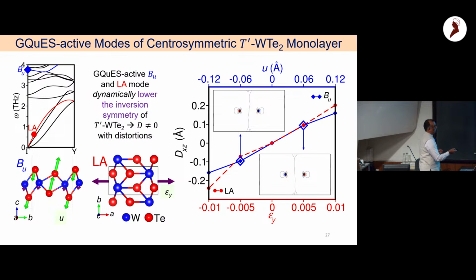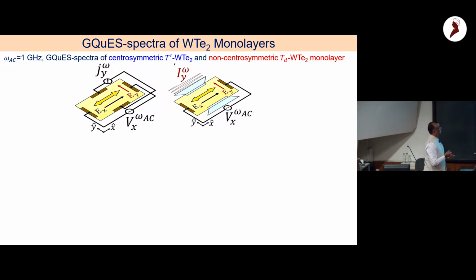What it means is, I'm showing you the displacement of atoms involved in these vibrations. This is the optical mode, this is the longitudinal one, the strain mode, and they will have non-trivial signatures in nonlinear Hall measurements. That's the prediction. The specific experimental setup we propose is a Hall measurement where you apply an AC electric field along these two electrodes and measure the nonlinear Hall effect along these two electrodes. If the frequencies are high, in terahertz, you will not be able to do the Hall measurement in this simple way.